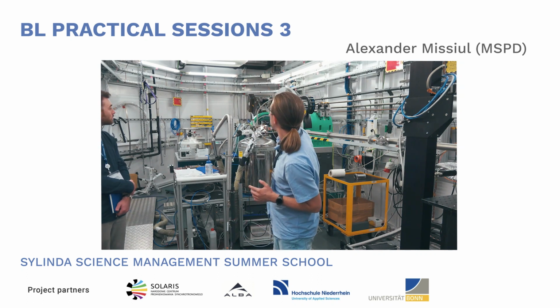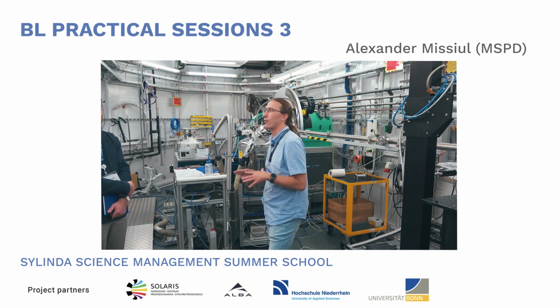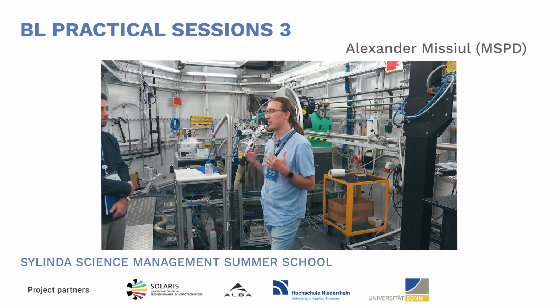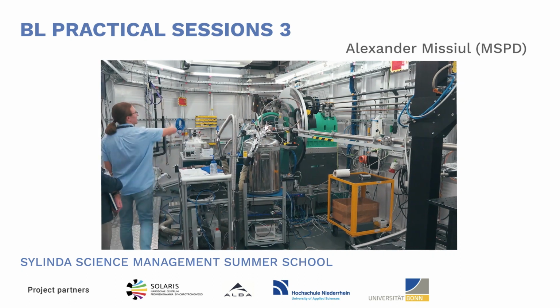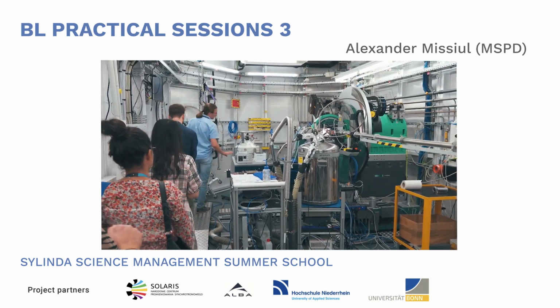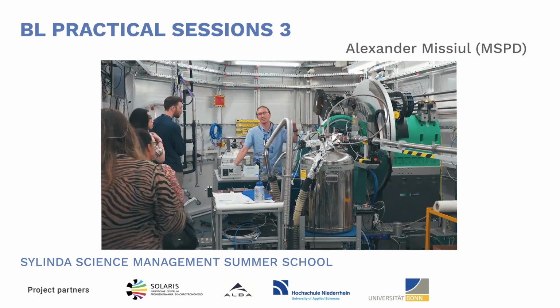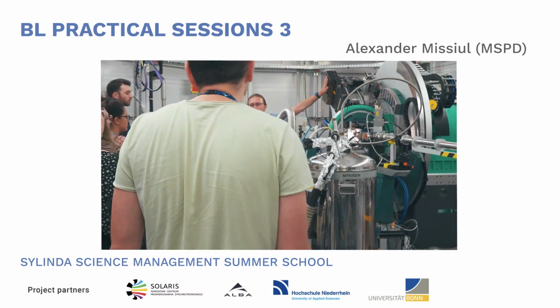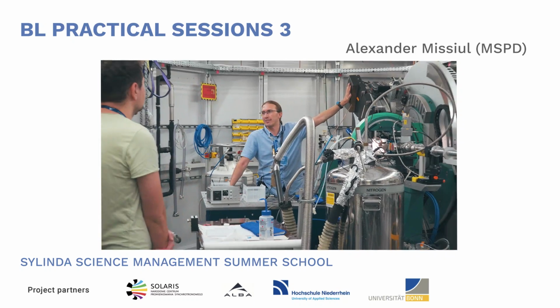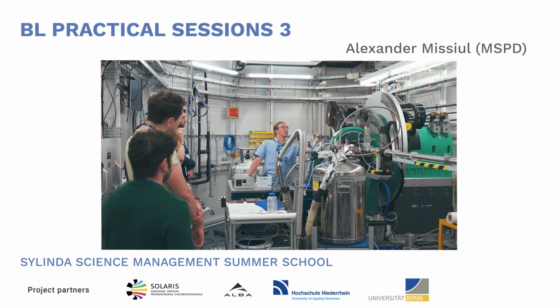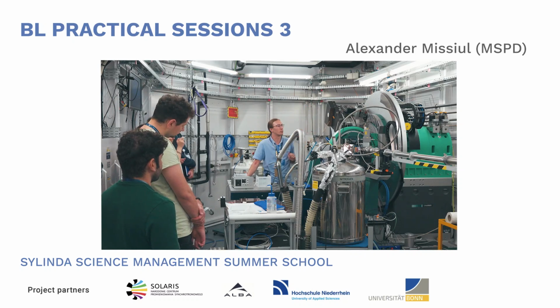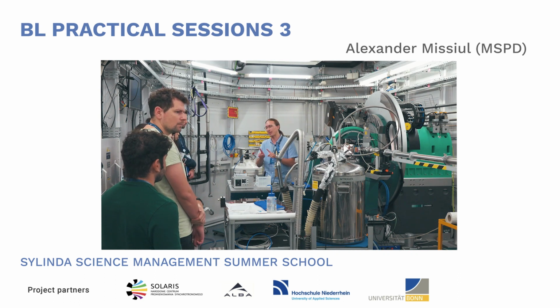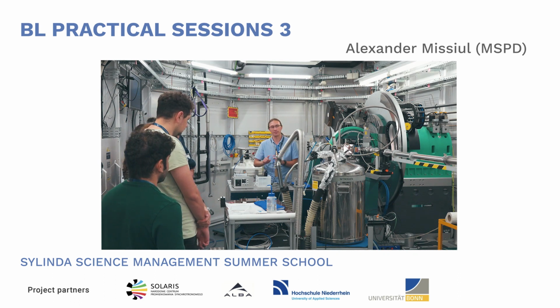Another station over there in the back is designed for more classical experiments, something that looks quite similar to what you might see with your laboratory diffractometer. So we have a goniometer, we can scan the angles with the detector, and we have essentially two detectors here. The one on top is a high resolution point detector. Here we really have to scan it across the angles to collect good data, but the positive thing is that the angular resolution is extremely high. We can separate very close peaks.